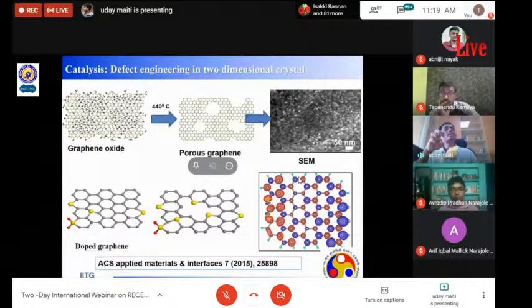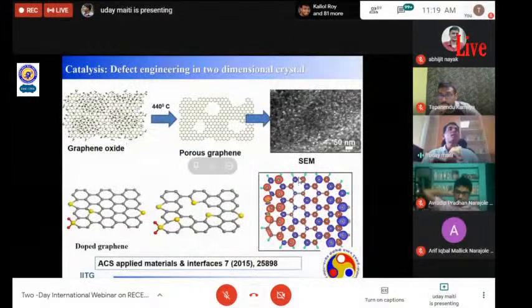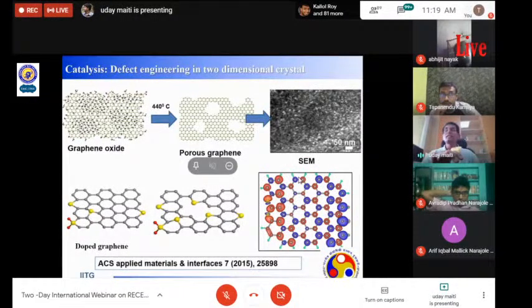Now we took this as important information, that because it has 2 percolated regions, if we heat the graphene oxide, then we can expect the 2 different regions to behave differently due to their 2 different chemical structures. They have 2 different burning points. So we controlled the temperature, 440 degrees Celsius, and found that those functionalized regions, those most disordered regions, burn first. As a result, we can create some holes. These are the holes, very tiny holes we can create.